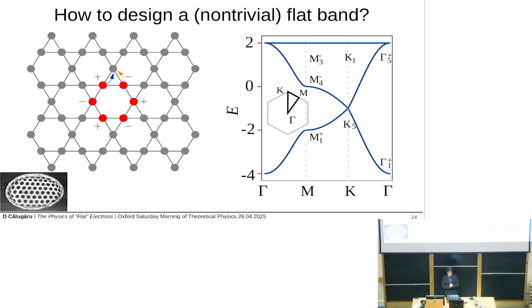Let's now look at a concrete example, the Kagome lattice. This is actually named after a traditional Japanese basket weaving pattern, which I'm showing here on the bottom left. At first glance, and if you remember the very beginning of the talk, you might think, well, why not just have independent atoms? Because independent atoms are by definition a flat band, but then those would be by definition topologically trivial, so uninteresting. So we want to build flat bands in some sort of a dynamic way from quantum interference. In the Kagome lattice that I'm showing here, you can write something called a compact localized state, and I'm showing this here in red.